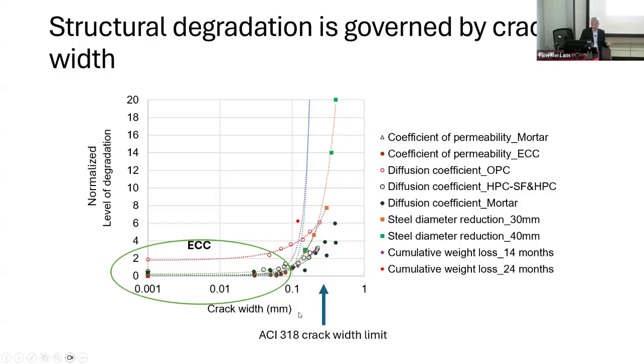Look at what happened. At very low crack widths, below 100 micron, 0.1 millimeter is 100 micron, below that level, the change is very little, almost flat, these curves, which means that at very tight crack width, degradation is almost non-existent. The material behaves as if there were no cracks at all. It doesn't see the presence of the cracks. However, once you pass the 100 micron mark, threshold, if you will, suddenly all these curves shoot up, okay? Degradation goes up very, very fast. They are not linear. They respond to crack width in a very highly nonlinear manner, okay?